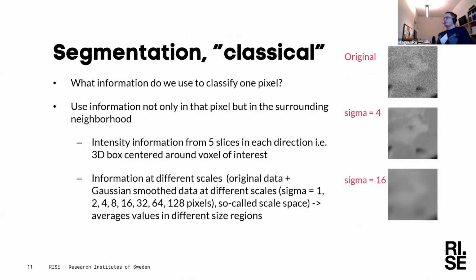So we started doing what I would refer to as a classical machine learning approach, where you do manual feature engineering. We looked at what kind of information we need to classify one pixel, and we found out that we need to incorporate neighborhood information. So in this first approach, we extracted intensity information from 5 slices in each direction from the voxel of interest, and also in the XY plane. So we extract information from the plane, but for several different slices. So we get a 3D box, which is centered around the voxel of interest.